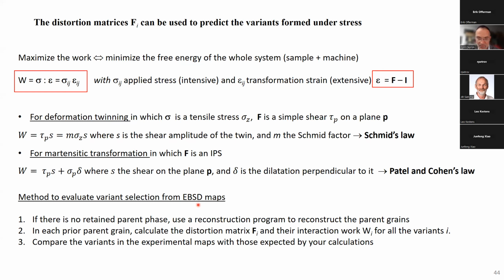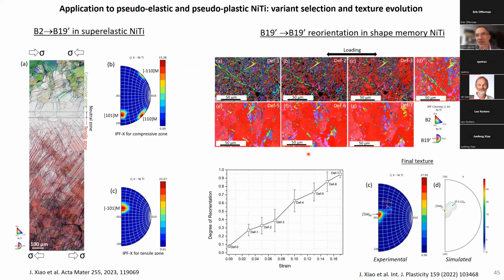So if you want to do that, if you have an EBSD map with martensite formed by a stress, what you have to do is to reconstruct the prior parent grains if you have no retained parent phase. Then you can calculate all the distortion matrices of all the variants. You calculate the interaction work for all of them. And in your map, you should observe the variants that have the maximum interaction work. And it's what we did here with one of my PhD students, Yunfeng Xiao, in shape memory nitinol, for example.